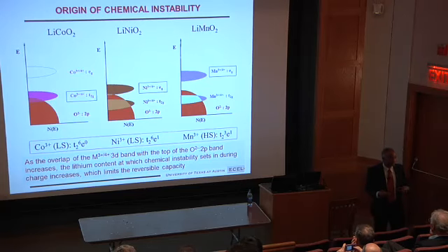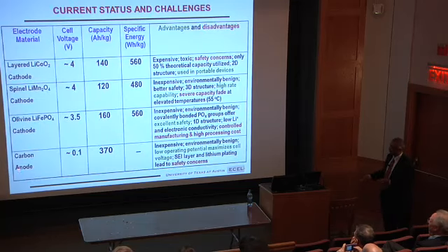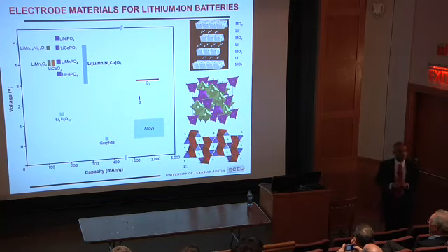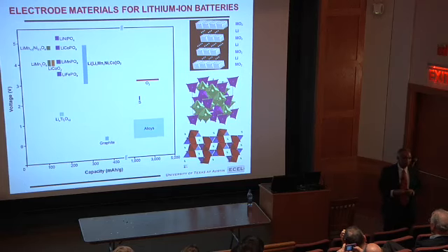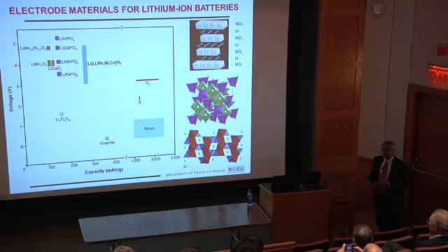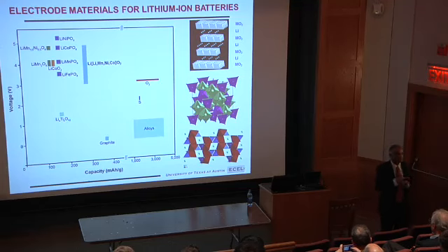Now, that does not start in the beginning. The real killer is this guy, carbon. Because the voltage is very close to this, when you do fast charge, or when you are in the winter, or even when you assemble the battery, this surface reacts with that organic electrolyte to form a surface film called the solid electrolyte interface layer. And that is not a good lithium ion conductor. When you try to charge fast, if the lithium ion cannot go through that interface, lithium will plate on the surface. When it plates, it doesn't plate smoothly, it plates like dendrite. When the dendrite is forming, you have a soft polymeric separator that separates the two electrodes. It will make a hole, short, all the current flows internally, that's the end of it.